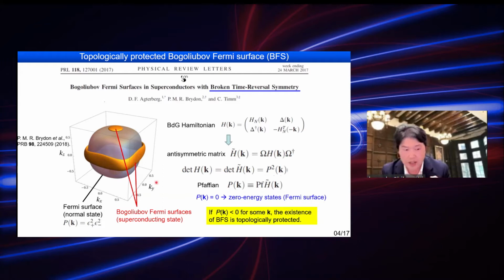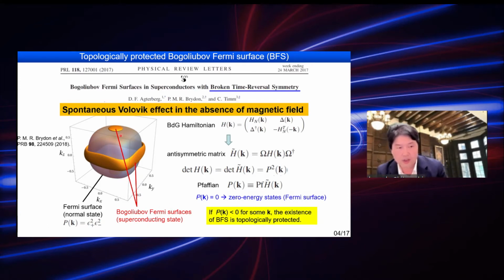For example, in this case, you can find this torus. Within this torus, you should have a negative Pfaffian. So if you go from inside the torus to outside the torus, you can find a solution where the Pfaffian becomes 0. That gives the Bogoliubov Fermi surface in the superconducting state. So this very interesting superconducting state can be considered as a spontaneous Volovik effect, which induces the zero energy state, even in the absence of magnetic field, if you have a broken time reversal symmetry in the superconducting state.